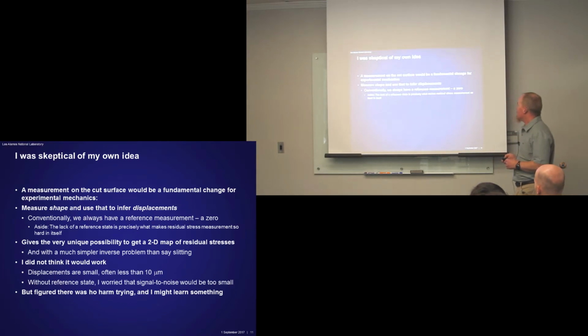I was pretty skeptical that it would work. A measurement on the cut surface would be really a fundamental difference from standard experimental mechanics. Almost everything we do, you take a reference measurement, you take a 0. You measure what something is before you deform it, then do your deformation and measure the difference, so you get a displacement. We have no reference there, right? That cut surface is not there beforehand. We're just going to measure a shape and infer displacements.